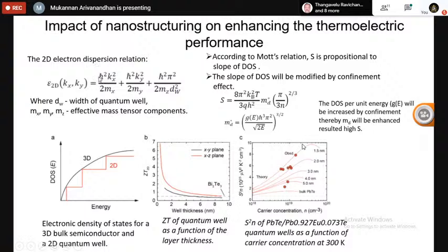The electrons are freely move with this wave vector along x-axis and y-axis, whereas this is the confined direction with the quantum well thickness of about d. Okay, and once if you have this kind of energy distribution, then the density of states will change like this. So the density of states is increased by the confinement.